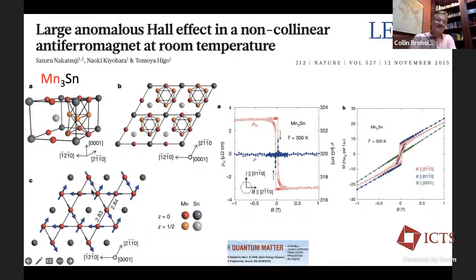We heard in Philip Mendel's talk about an insulating Kagome lattice material. In this case, it is a metallic material, which means that the interactions are much longer range, and therefore it actually does not end up being driven, if you will, by the kind of frustration that was mentioned in Philip's talk, because there are fairly strong interlayer interactions. It's a really fully three-dimensional antiferromagnetic material, and it's really important for us to keep that in mind.